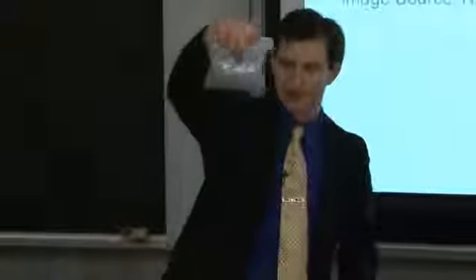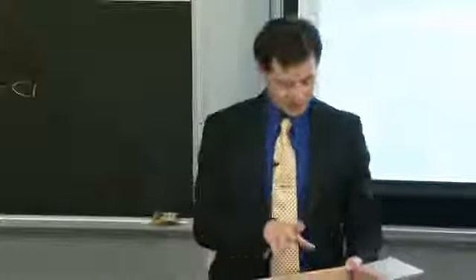The seeding rod is silicon? It's actually doped silicon, so it's lower resistivity, so you can pass more current through it. This here is chunks, or smaller chunks, of the polysilicon. So it's essentially just crushed polysilicon. And if you're trying to load a crucible with big chunks like this, you'll leave a lot of empty space unless you crush some of this up and make finer grains out of it and fill in the gaps. So I'll pass these around right here, so you can have a look at them.